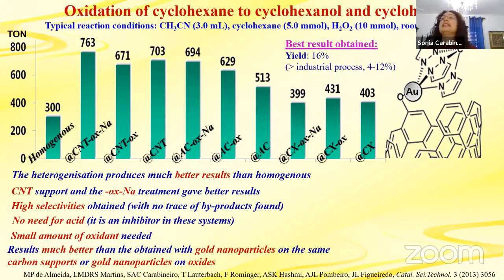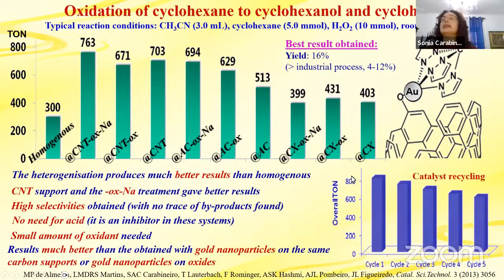So that was interesting. The best result obtained was a yield of 16%, which is higher than the industrial process. And remember, the industrial process needed 150 degrees, and we could do it at room temperature and only in 6 hours. So it's quite good. And we could also obtain a good catalyst recyclability, because you see here that after a few cycles, of course, there is a small loss of activity that's due to a small leaching, but we can recycle it. If we used homogeneously only the support, we could not recycle, we could not obtain it back.